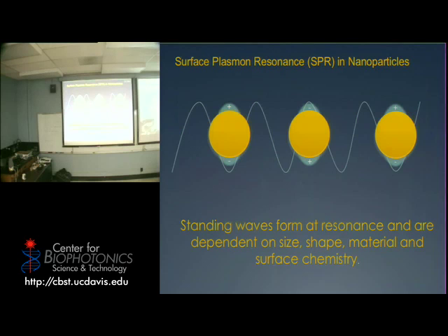And light is essentially an electric field that is moving up and down, and you have these electrons that try to align with it, right? So say here the field is positive, so the electrons want to go there, so one side of the particle becomes negative and the other one is positive, and they go back and forth. But say the free path is 50 nanometers and the particle is 20, they cannot move that much. So the best example I could come up with is the tennis player or the football player that runs left and right very fast when he's doing a drill, and then as he moves from one position to another, he kind of skids with the shoes, right? So that's kind of the same thing.